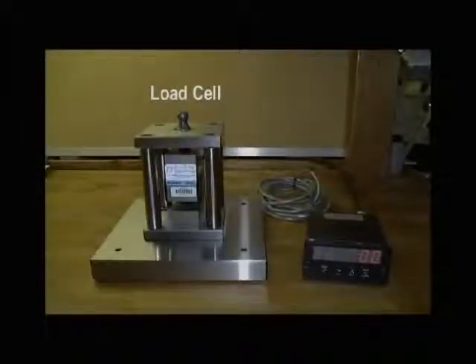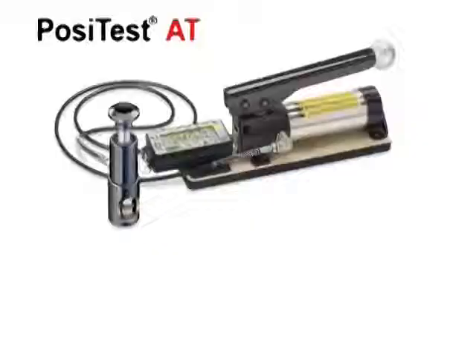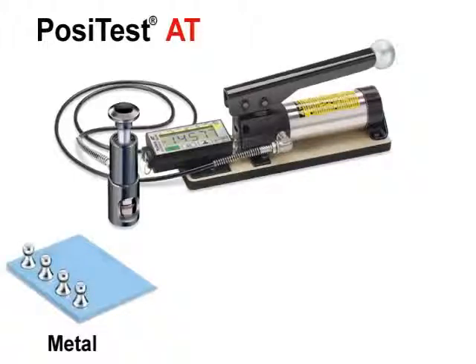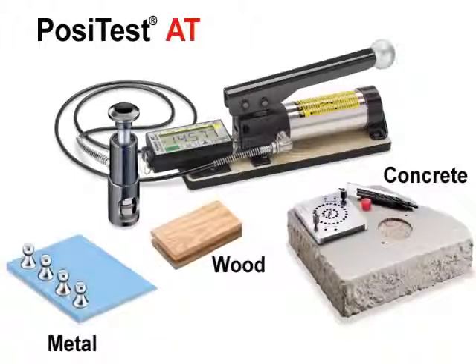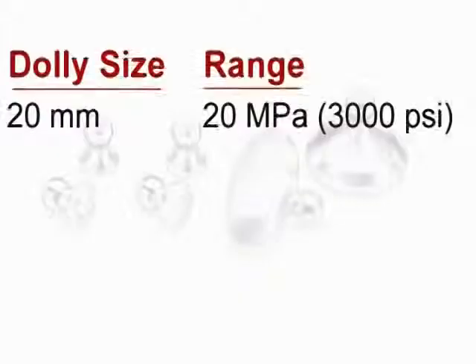Every PosiTest adhesion tester pressure system is calibrated and certified to plus or minus 1% full-scale accuracy using a NIST traceable load cell. The PosiTest ATA measures adhesion on a variety of coatings and substrates, including metal, concrete, wood, and plastic. With the included 20 mm dollies, the PosiTest ATA has a range of up to 20 megapascals, 3,000 pounds per square inch.